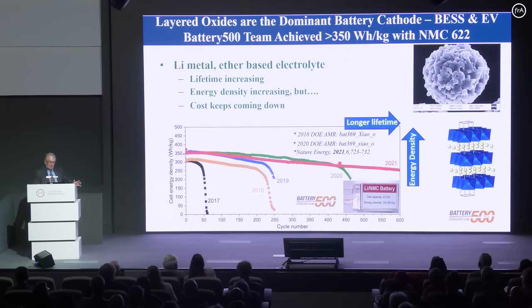It's about 6 universities and 4 national labs, so it's a big national consortium. And the data is in what we call these little pouch cells. It's one of my ex-students, Jay Xiao, who's in charge of this. And these are real numbers. I emphasize that because a challenge in this field is there's far more hype than reality. But these are real numbers, because what we do is actually weigh the cell, measure its volume, and these are the numbers that come out. So we're on the right target. Our goal is to get to 500, and we've got more than halfway there in the first 5 years.